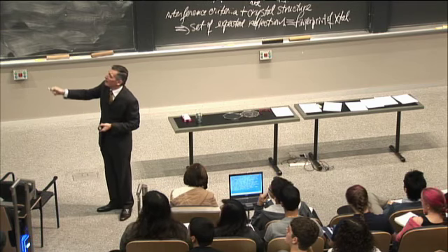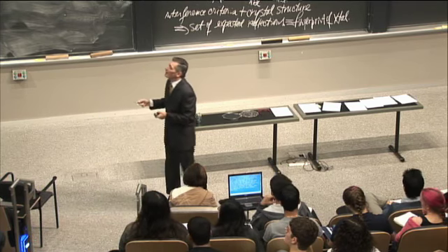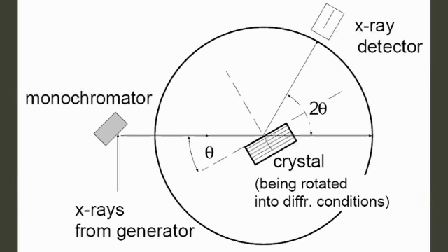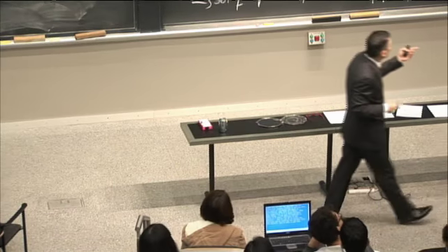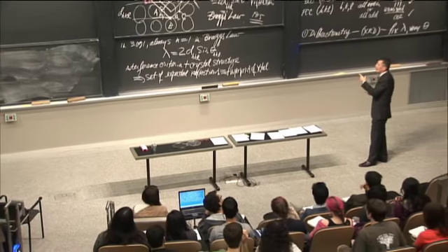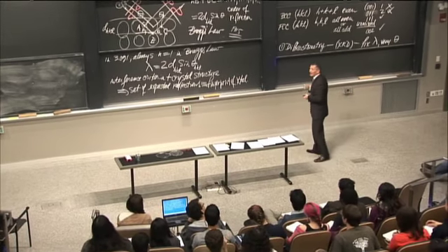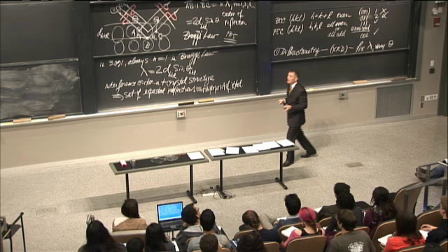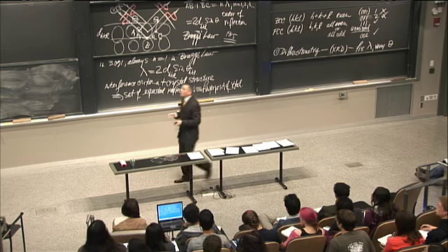So you'll see X-ray data usually reported in units of 2 theta, and here's the detector. Then all you do is rotate the specimen, and by rotating the specimen with the detector, you're able to get the entire set of reflections. Whenever you move through an angle that satisfies the Bragg law, you get a peak in intensity. And here's what the output would look like.